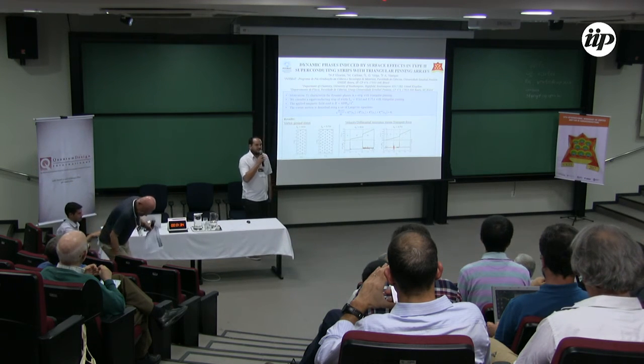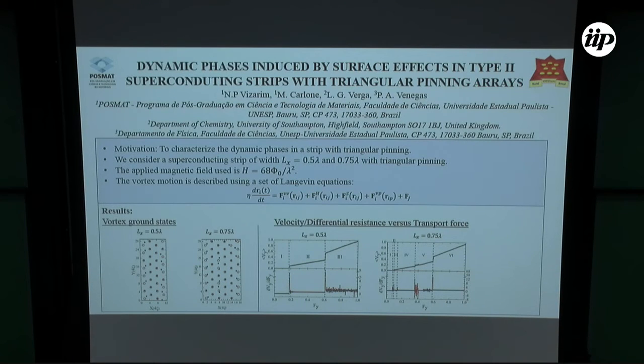Good evening, everyone. My name is Nicolas Vizarin. I'm here to talk about the dynamic phases induced by surface effects in type 2 superconducting strips with triangular pinning arrays. This work isn't done, so we're open to suggestions and ideas. The motivation is to characterize the vortex dynamic phases in a superconducting strip. We're especially interested in the surface effects on the dynamic phases. So we consider superconducting strips of 2 widths, 0.5 lambda and 0.75 lambda, both with triangular pinning. We consider the 2 samples with the same parameters: the same applied magnetic field, which is 68 phi0 per lambda square, the same pinning density, same pinning size, and same pinning strength for both samples. We're just using the width as a variable.